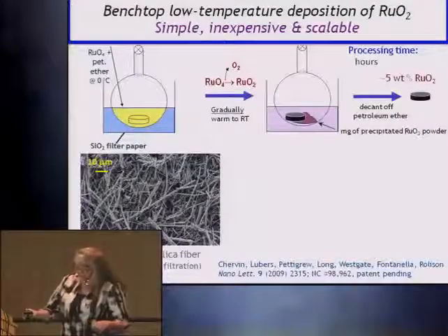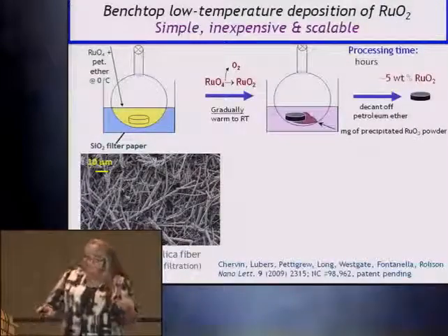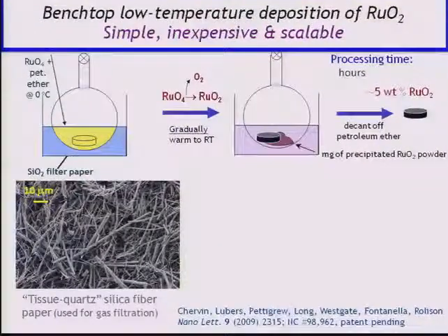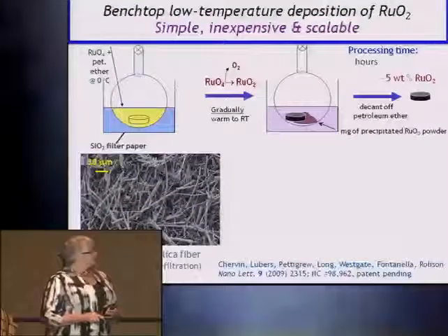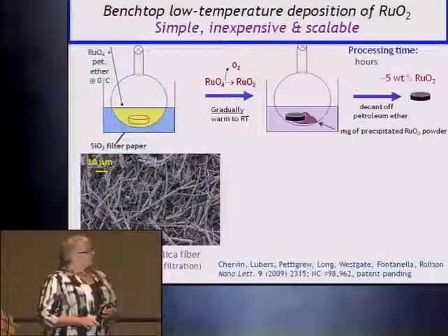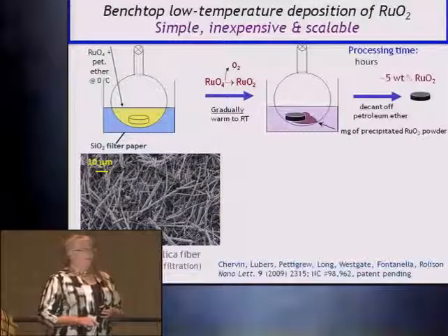Well, we still wanted to get the ruthenium used, but a little bit less of it than bulk, because it is a platinum group metal, and worked out a way to wire 2 nanometer high RuO2 webs throughout a silica aerogel. Published that in Nature in 2000. Took more than a week to make, and it was a total pain. So Chris Chervin adapted the protocol, but now on the benchtop, out of petroleum ether, at sub-0 degree temperatures, but used quartz silica gas diffusion paper.